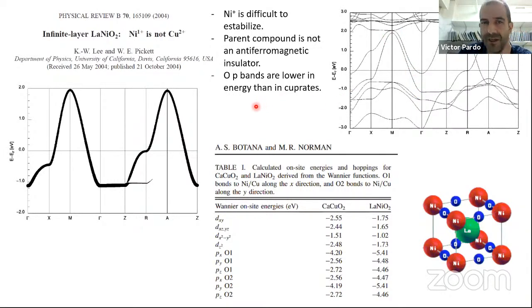And people realized really soon that also in these nickelates, the oxygen p bands are farther away from the Fermi level than in the cuprates. You can see actual calculations more recent by Antia Botana and Mike Norman. What they calculated was the on-site energies of the d bands and the p bands. And in the cuprates, they are in the same energy range. But in the nickelates, this is not the case. In the nickelates, the oxygen p bands are much lower in energy.